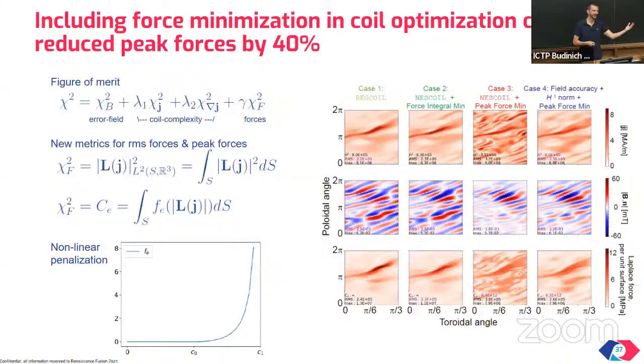This is something that was not studied in other stellarators before because they were operating at lower fields. But now, thanks to high temperature superconductors, we go to 10 Tesla. Let's say we double the field, in principle, we quadruple the forces if we don't change anything else. In reality, compared to present experiments, we are quadrupling the field and therefore, in principle, going up by a factor of 16 in forces. Again, if we don't change anything else. But based on the fact that there are many approximate solutions, you can properly define an optimization metric, a force minimization metric,